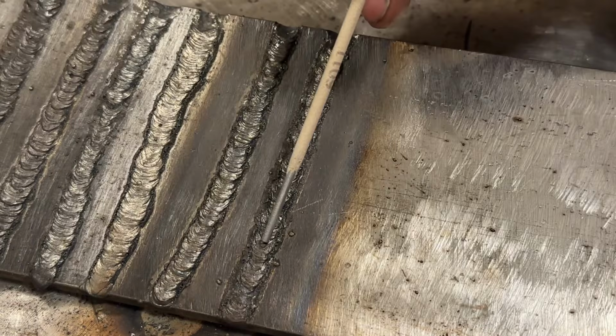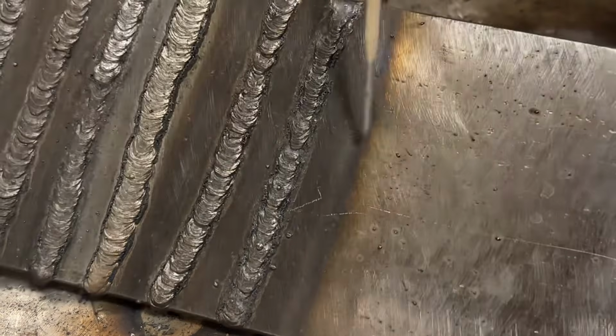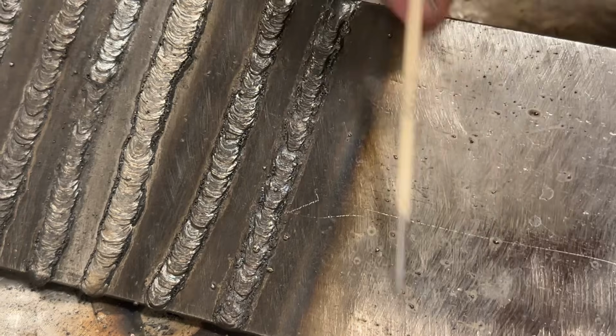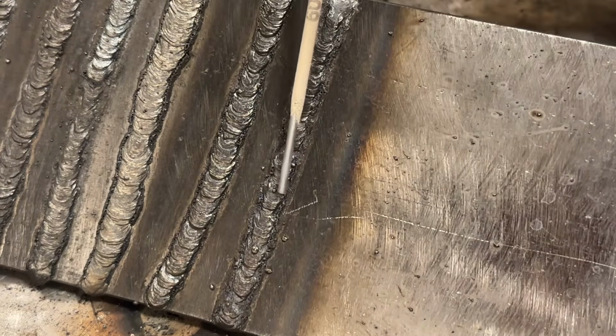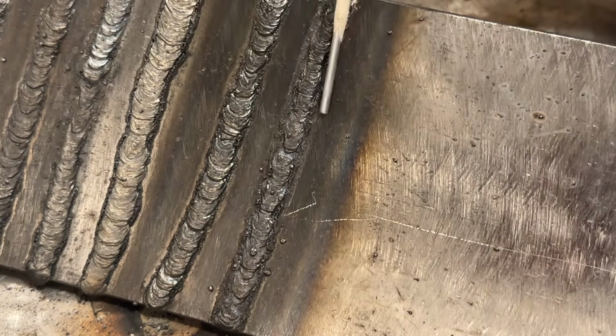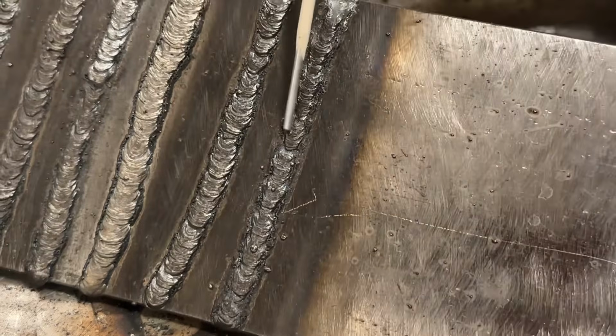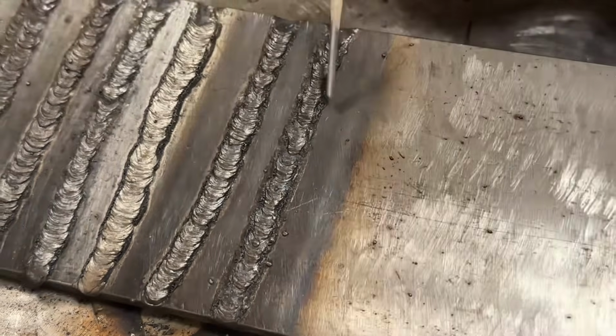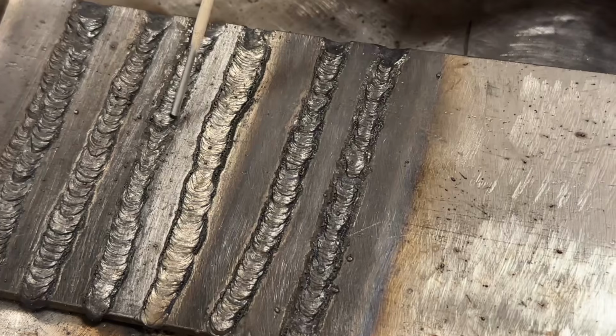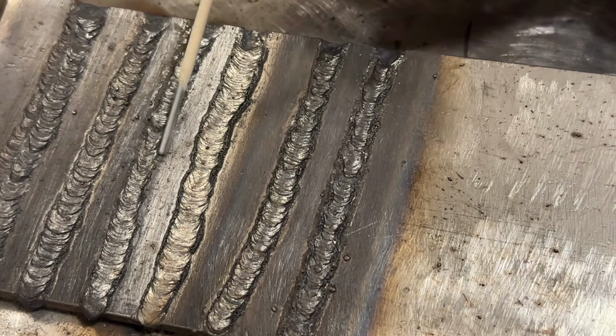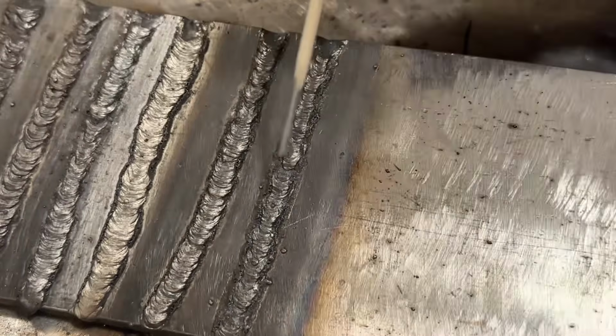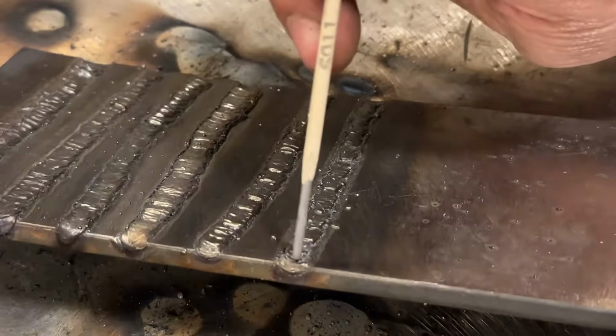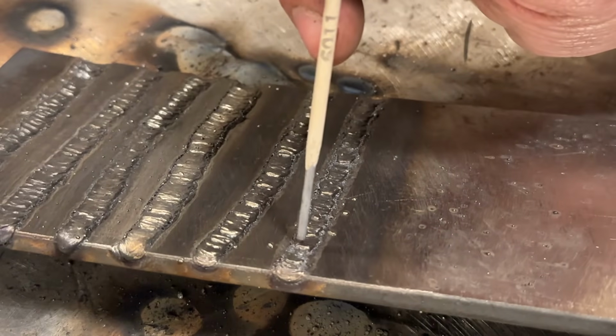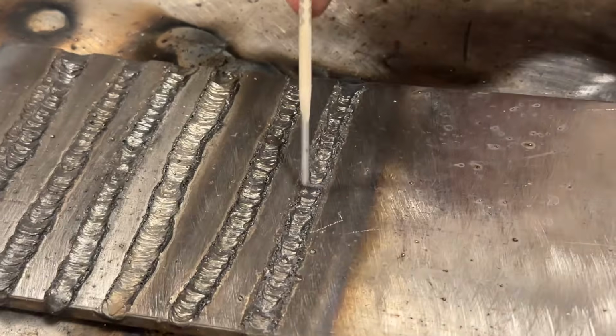Now, if you notice here, look, hard spatter, hard spatter. It's hard to tell, but there's a ton of spatter down here. There's spatter on top of the weld, like all over the place. And that weld looks pretty gnarly. Like I would say that that's not acceptable. It looks very much like over here. And yet this, I kept a very consistent arc gap, just too long. And you can see what happens.